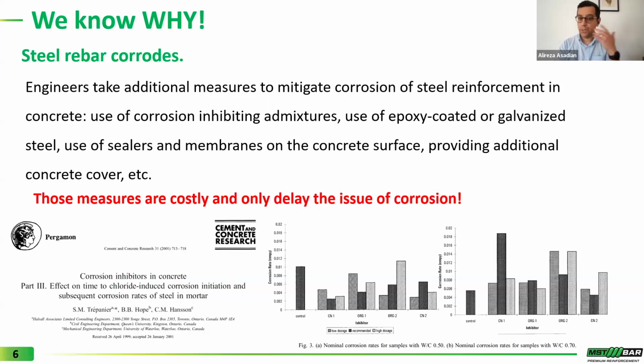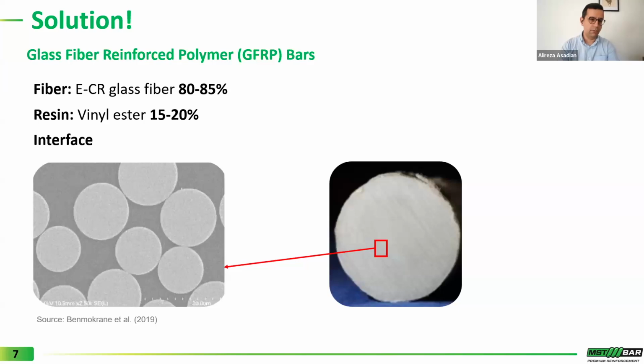Engineers take additional measures to mitigate the issue of corrosion in reinforced concrete structures. Those measures are, for example, use of corrosion inhibitor admixtures in concrete, or use of alternative reinforcing bars such as epoxy-coated, galvanized, or stainless steel rebar, use of sealers and membranes on concrete surface, or providing additional concrete cover, and so on and so forth. It's, however, very important to know that those measures are, first of all, costly. They will add to the initial cost of the project. And more importantly, research has shown that many of those measures can only delay the issue of corrosion in best case scenarios and will not eliminate the corrosion issue in reinforced concrete structures.